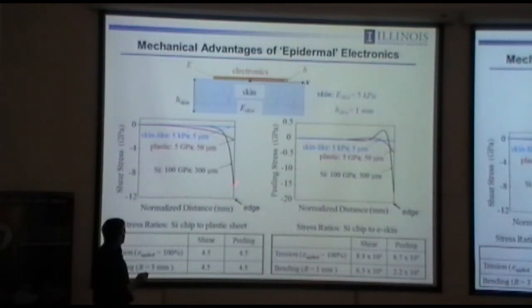So silicon has the highest peak stress, and the peaks in the case of the shear stress develop at the edges. So delamination would start at the edge with the case of silicon, and it would start early because there's very large stresses there. Plastic substrate, flexible electronics, you have an improvement, and then skin-like is even further improved. That's partly because the modulus is being driven down, partly because of the thickness. So you have this trend line, same thing you see in the peeling stresses. Silicon chip is the worst, flexible electronics is next. Skin-like is next. But the point that I want to make here is around the magnitudes of these trends, not the overall qualitative trend, because you could probably just guess that, don't even do the calculation.